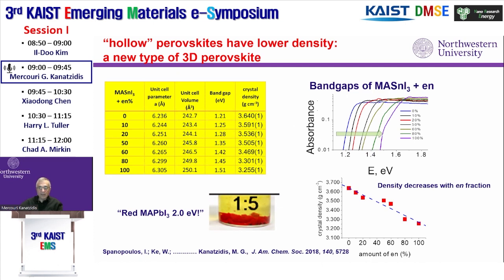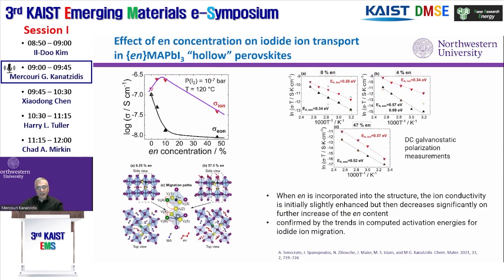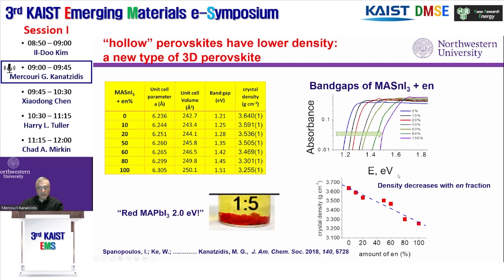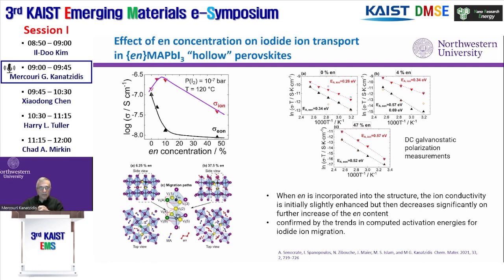It explains the wider band gap because it's not really as three-dimensional as before. And the presence of ethylene diammonium was verified by dissolving the crystals in DMSO and doing NMR spectroscopy and seeing that they are there. These materials are far more stable than the corresponding 3D materials because, as we did this collaboration work with Saiful Islam, now at Oxford University, and Joachim Maier at the Max Planck Institute in Stuttgart, we realized that these are far more stable, and the reason they are more stable is because the ion migration is frustrated inside.